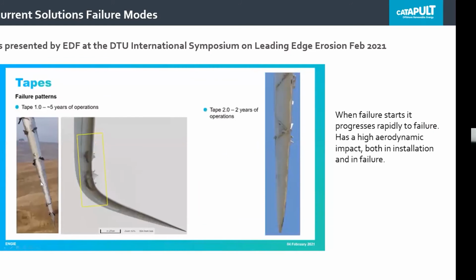The tapes, as you can see on the left, the tape 1.0 was the original aerospace tape, which actually had really good performance. It lasted about 5 years of operation offshore. So that's actually probably the best recorded performance so far of any solution. The Polytech L is as yet unknown. The 2.0 tape that they replaced it with, the W8750, has actually suffered really early failures, after only 2 years, and you can see that when it's failing, it has a really high effect on the aerodynamics. And this is something else to consider in terms of solution.